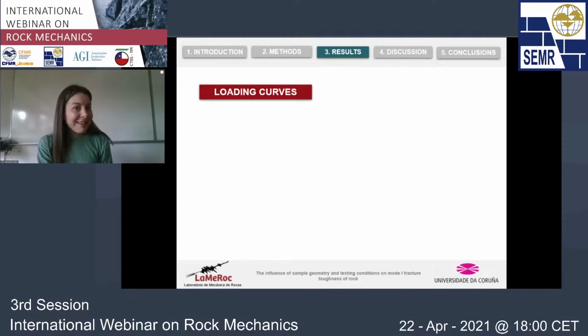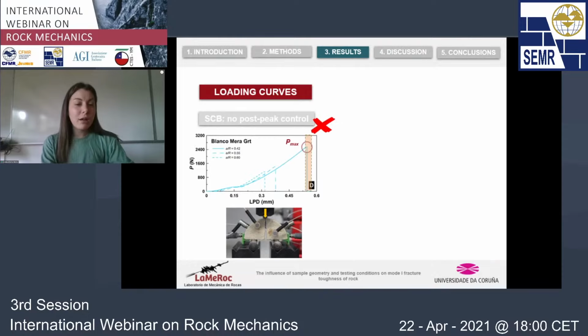But there is something really interesting about the comparison between the 2 testing methods, which is the shape of the loading curves. So these are some examples for the case of the SCB. And we see here that as the load point displacement, which is the displacement given by this roller here on the top of the sample, increases, the load increases up to a point when the peak value is achieved. And after this moment, fracture propagation is so quick that we cannot control this process. So the sample fails immediately, and the load decreases at this moment to 0.